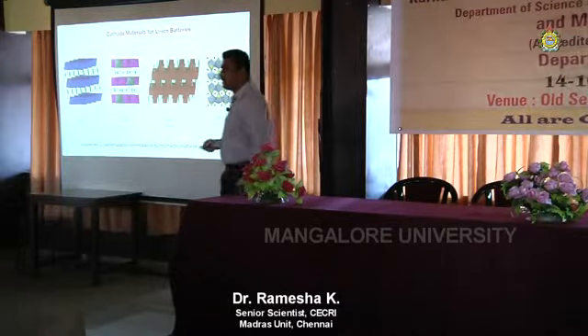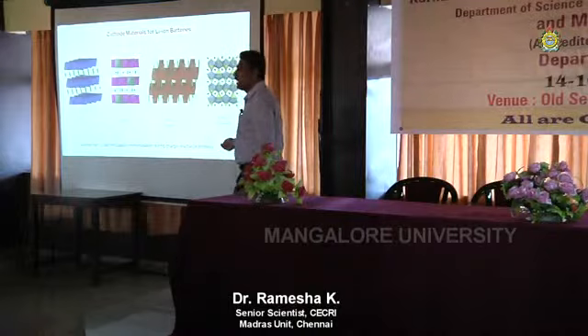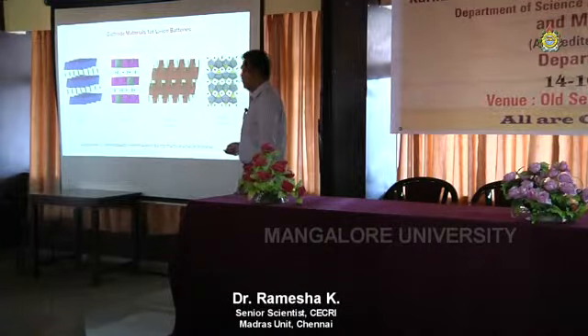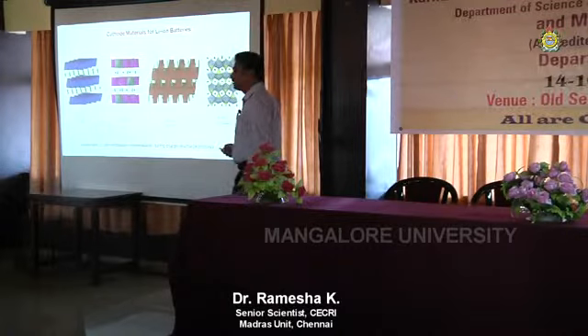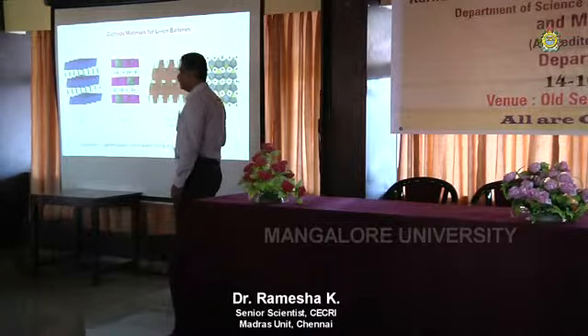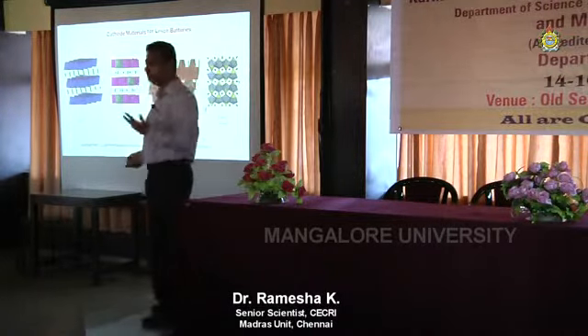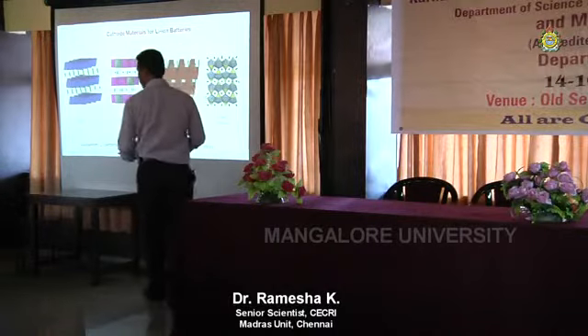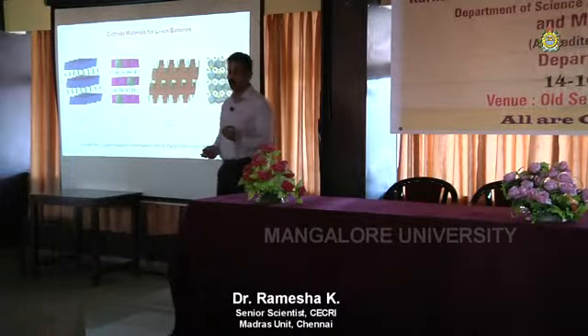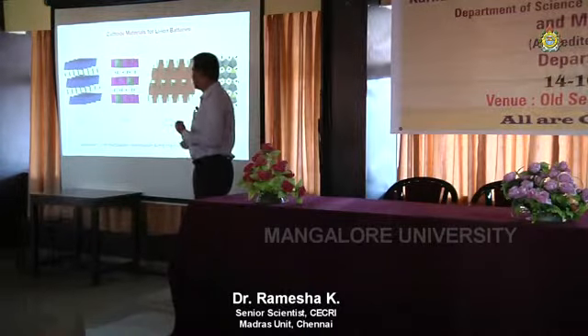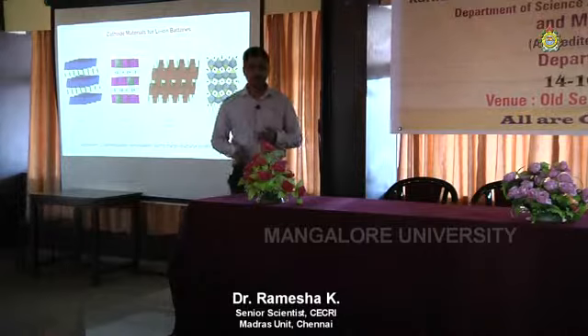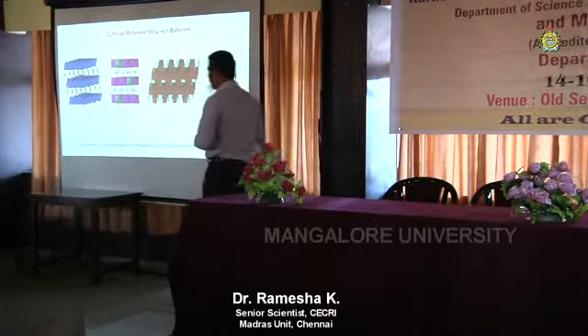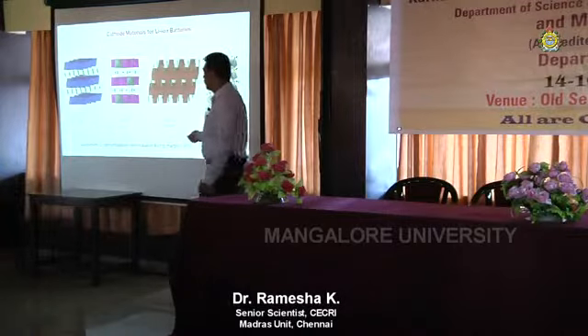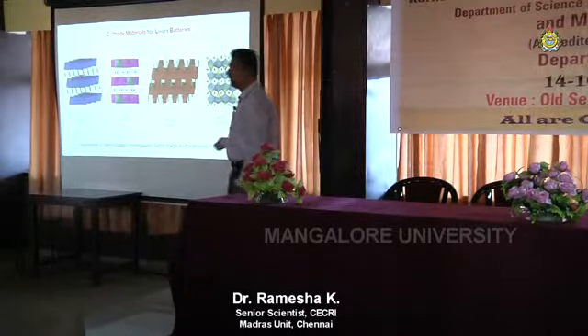And again, I will tell you that this is not something we identified for the first time. The compound was known, but people discarded it because, see here, manganese is 4+, right? You cannot oxidize manganese 4+ any more. If you do it, it goes into solution. It cannot stay solid. So people disregarded this as a battery material. But then we figured out that this can be used in batteries, and we showed that it has double the capacity of all known materials. I will come back to that a little later.